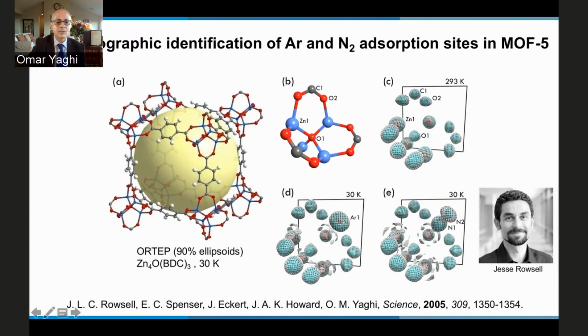Here you see an ORTEP with 90% ellipsoids of the framework of MOF5. Very well behaved atoms, and they can be determined with precision. You see here one of the adsorptive sites, without anything in the pore, absolutely no guests. So you see the electron density of the atoms representing the metal oxide unit. However, as you introduce argon or nitrogen, you see the electron density of argon settling in around the adsorptive site, which is on the metal oxide unit. So does nitrogen. These experiments allowed us to figure out what the adsorptive sites within MOFs are, and then understand why they have such a high surface area